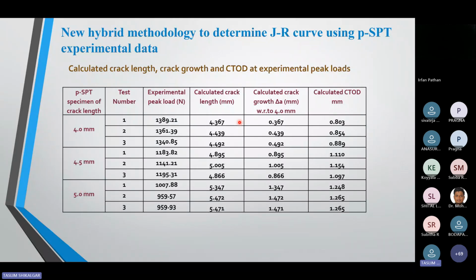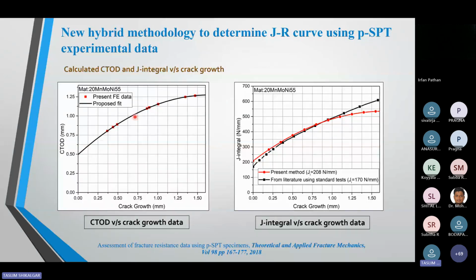But here I calculated crack growth with respect to only the 4 mm specimens. So this is the crack growth observed during the specimens with the help of correlations. And this is the calculated CTOD at the experimental peak load. Here I plotted these points and extrapolated these curves. So I got the CTOD initiation as well as the whole curve, CTOD as a function of the crack growth. And these are the fracture properties for these respective materials.